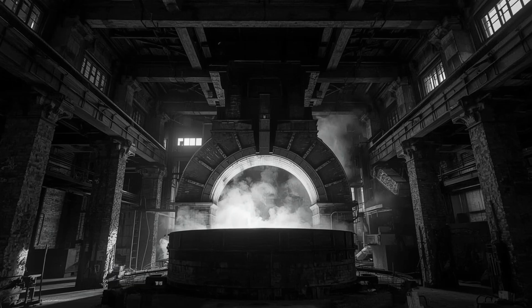When the brick shrinks under constraint, the structure doesn't simply get smaller uniformly. Instead, stress concentrates in particular zones, especially where the iron bands attach and where changes in wall thickness occur. These stress zones experience additional compression, which can cause creep, the slow, permanent deformation of materials under sustained load. Creep is a known phenomenon in metals at high temperature, but it also occurs in ceramic materials like refractory brick. Under enough pressure, maintained for enough time, the brick doesn't just shrink from moisture loss, it deforms, compressing further under its own weight and the constraint of the iron framework. This compression is permanent. Even if the furnace were shut down and allowed to cool, the brick wouldn't spring back. The dimensional change is locked in.